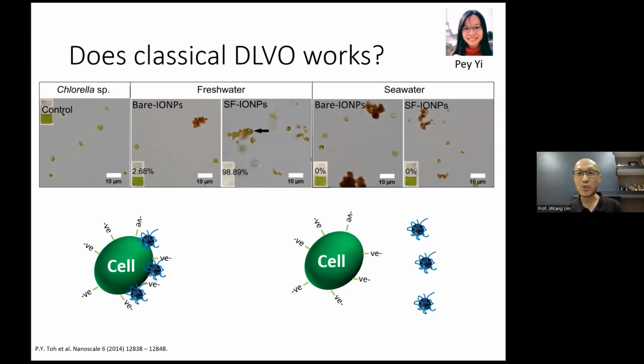Later on, we shifted our attention to seawater species, because microalgae not only appear in rivers, they also appear in the seas. We wanted to expand the application to separate microalgae not only in freshwater conditions, but also in seawater conditions. And actually our strategy failed, and it failed very miserably. This is counterintuitive, because seawater is full of free ionic species.